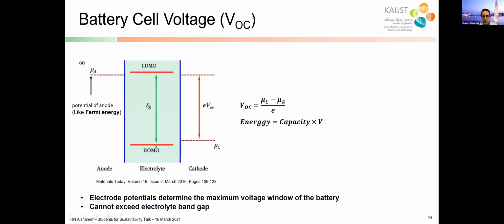And that's one issue. So actually for lithium-ion batteries, people have identified anode and cathode that will give you a 4.7 volt voltage window, but the electrolyte cannot take it. That's why the lithium-ion battery runs much lower than that, 3.7 or 4.1 volts. This is limited by the electrolyte. So if one can develop an electrolyte that can go to 4 or 5 volts, then they can significantly increase the energy density of the lithium-ion battery.